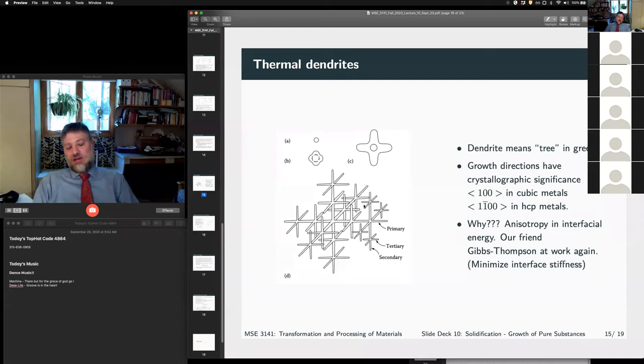Anything more than that, we're in the regime of alloy solidification, where we get dendrites that are due to compositional variation. And the fact that when we freeze and solidify, we reject solute from the solid into the liquid. We reject the impurities out. So these thermal dendrites are very important from a theoretical point of view, much like homogeneous nucleation is very important from a thermodynamic point of view, but they're never really seen in practice. So that's important to keep in mind.